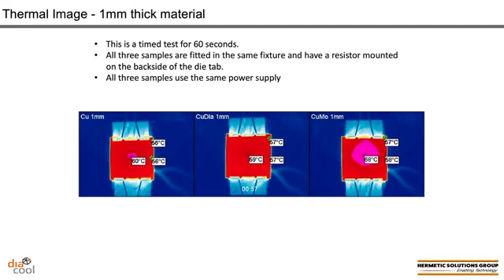The interesting thing to look at here is the thermal gradient across the three substrates. So moving from the left, look at the copper sample, you'll see that there's a thermal gradient of around 3 degrees centigrade from the center of the part on the opposite side of that resistor to the edge of the part. But you can see a significant hotspot developed in the center of that substrate. Over on the right-hand side, the copper moly sample has a very large hotspot area. But more importantly, you can see the lack of thermal spreading of the copper moly material. You can see a thermal gradient here of around 10 and 11 degrees centigrade from the edge of the substrate to the center. Where in the middle, this Diacool product line shows very even thermal flux across the entire substrate, and there is essentially no thermal gradient, depicting that this material is a very effective heat spreader both in X, Y, and Z directions.